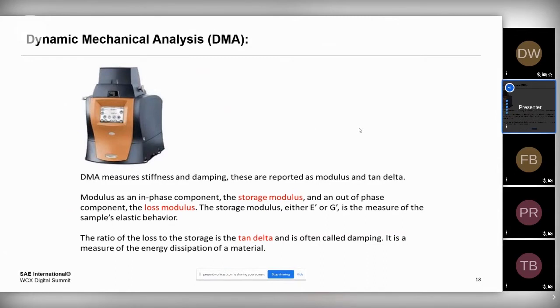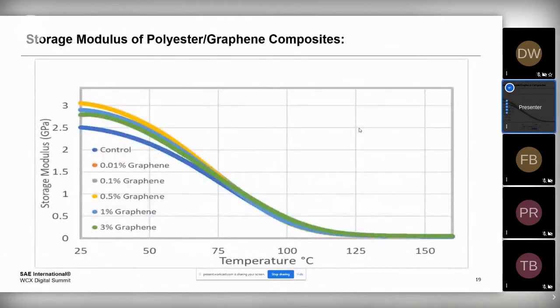And there has to be the whole process from the manufacture of the graphene to the point where you actually mold your final part or coating, apply your coating, really makes a difference in terms of what types of properties you achieve. So one of the things we did here was a dynamic mechanical analysis study, and we looked at what happens when you take a polyester graphene composite, in this case, and we looked at different loadings to see what impact it has on the modulus.